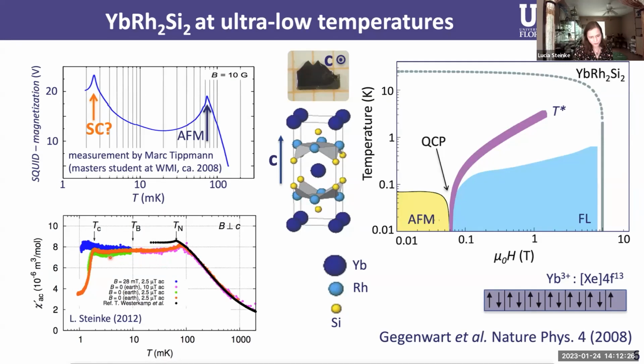And that also shows a signature that is characteristic of a superconductor, and that is a drop towards reduced magnetism. In a textbook superconductor, that would go all the way negative to basically perfect diamagnetism. In this case, it doesn't go all the way negative, but it's not completely surprising considering the sample is magnetic. So that's a good indication that we could have a superconductor here.